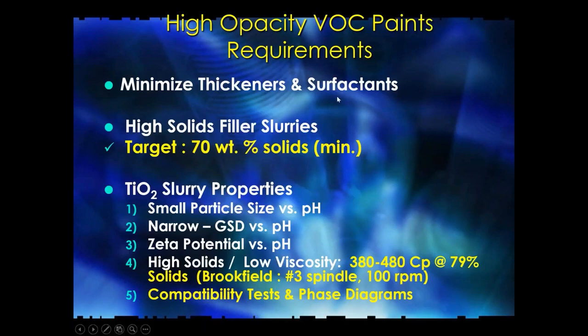Now, why do we want to go for very high solids? It's because the resins come in with a lot of water. If you have a lot of water, the big headache in 2010 was, oh my God, I can't get my KUs. Oh, I can't get my ICIs. How am I going to thicken this product up? And fortunately, some great companies came along and developed products that thicken. But it didn't take into consideration whether or not I'm causing a depletion type TiO2 agglomerating. So then you find problems with rub-ups. And there's going to be a lot of benchtop chemists sitting there looking at, yep, I know what you're saying, Glenn. We got it thick, but doggone it, when you went to do a touch-up, we got different color paints.